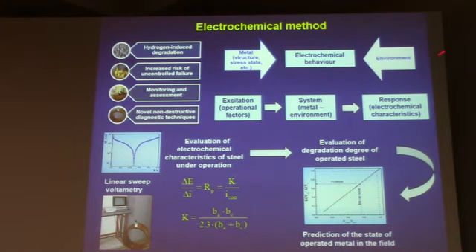It's known that metal environment system is characterized by electrochemical characteristics, and any changes in the system should cause a change in electrochemical behavior of a metal. And taking into account that long-term operation causes some changes in metal state, it should be expected that its electrochemical behavior will be changed too. And this aspect was used in a non-destructive electrochemical method for evaluation and prediction of the current technical state of the material. It should be also noted that electrochemical tests can be performed on any metal structure without the need of extracting of the material specimen for laboratory testing.